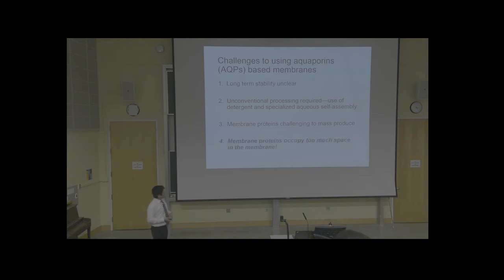So the fourth challenge is more technical. If you design this membrane, membrane proteins occupy too much space in the membrane. This sounds awkward, right? But if you want to design the membrane from the molecular scale, what's the ideal form for the membrane? We published this paper like two years ago. Like the 2D layers, Professor Binek's, you want to align these proteins very well with the highest packing density. Probably you can put them on the surface one by one, right? And actually we use membrane protein 2D crystals. This is the most packed protein we can find. So you align these membrane proteins one by one.